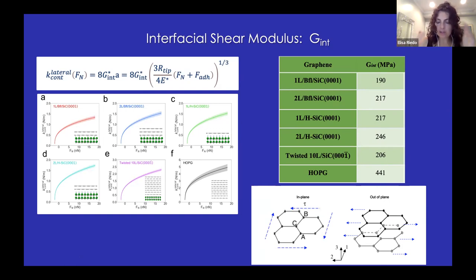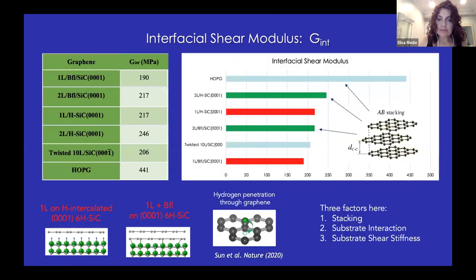And this makes sense, right? Because again, it's like having two springs, and one is extremely stiff and the other one is much softer. So what we measure is the soft spring. After that, let's try to understand what we have measured, and let's try to see how this interfacial shear modulus, which is an elastic constant, is related to the dissipation and to the atomic scale friction. So first of all, let's try to understand the origin of these numbers.